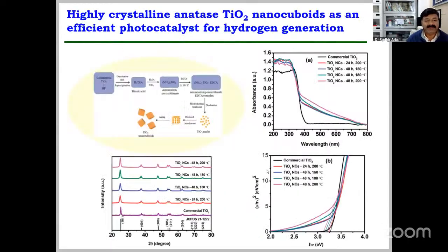Okay, another thing we did, we prepared this TiO2 at different temperatures and different reaction times. So here we prepared this TiO2 at 24 hours, 48 hours at 150 degrees, 48 hours at 180 degrees, 48 hours at 200 degrees. From the visible absorption spectra, we're getting different kinds of absorption behavior in the 400 to 700 nanometer region. It shows some extended absorbance in this region. And this must be beneficial for photo-related reactions from an application point of view.